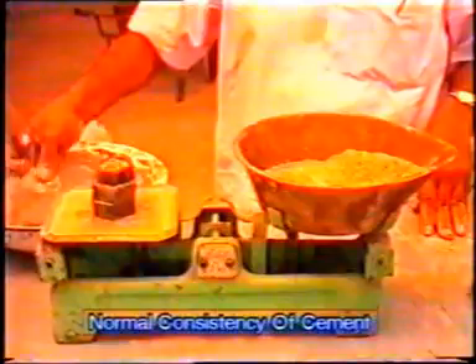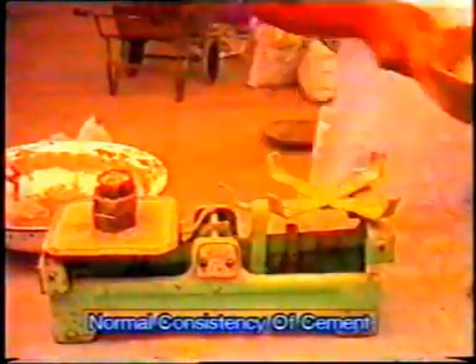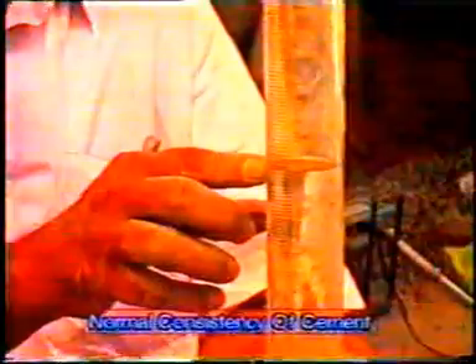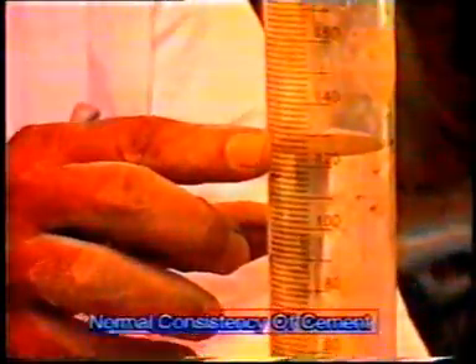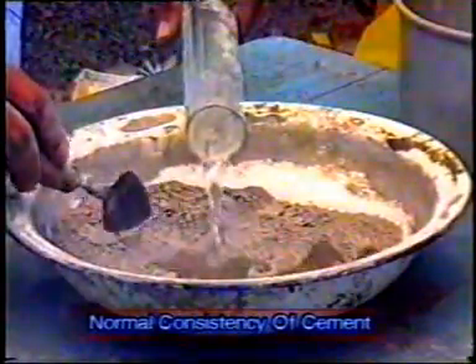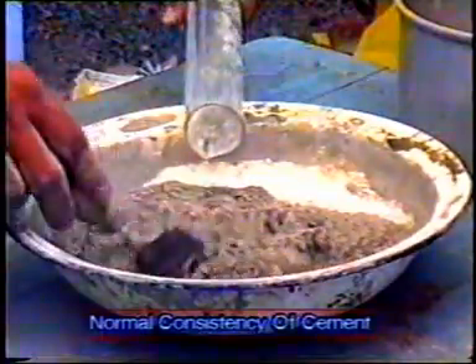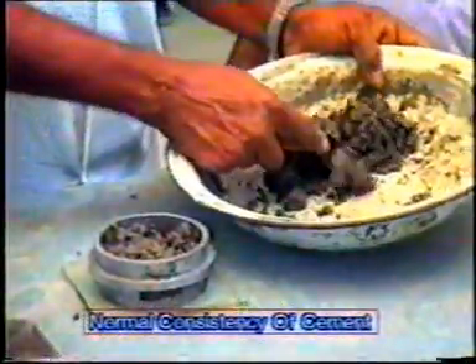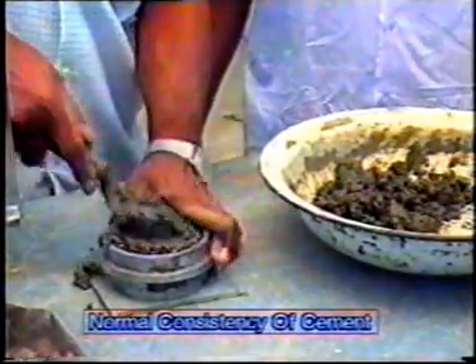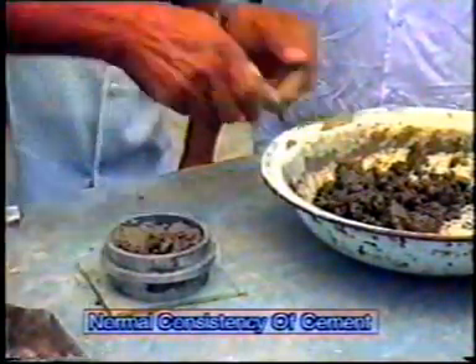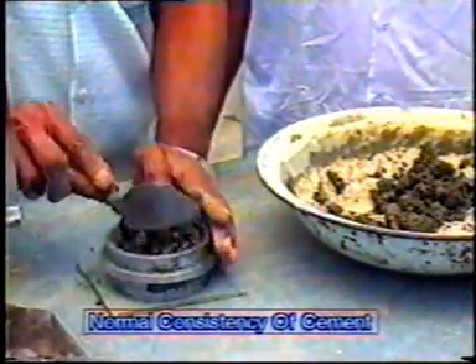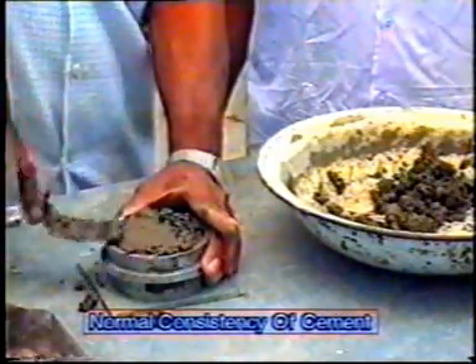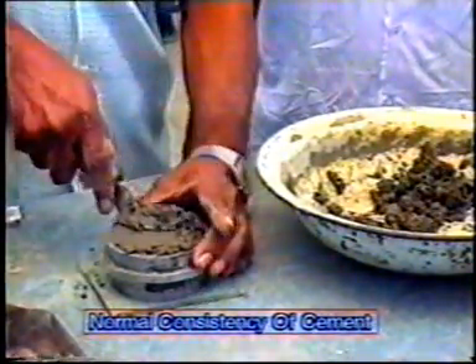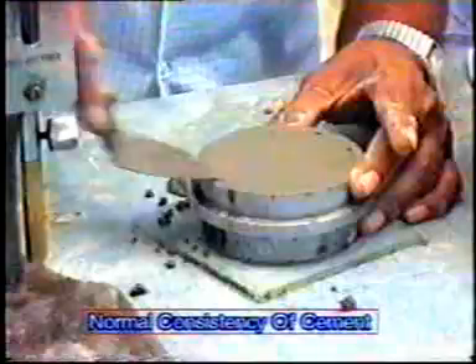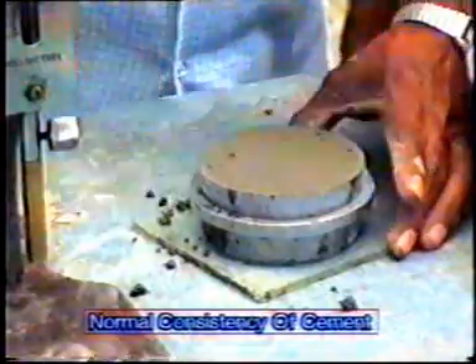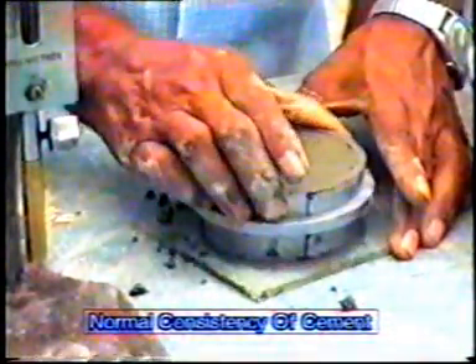Take 500 grams of cement. Now, as a first trial, prepare a paste by adding 25% of water by weight of cement. Fill the mold, placed on a non-porous plate, with the cement paste within 3 to 5 minutes from the time of addition of water to the cement. Shake the mold to expel the air.